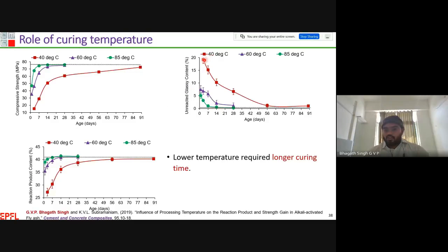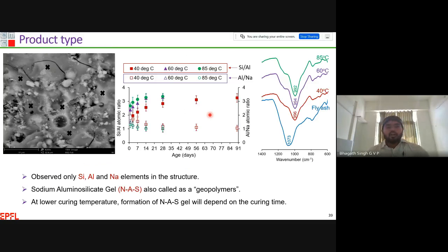We have three curing temperatures. At 40 degrees Celsius, you can see the dissolution is taking place very slowly. In the case of 60 to 85 degrees Celsius, you can see the dissolution is complete by 7 to 14 days. Again, we tried to identify which type of product is formed at these curing temperatures. If you increase the temperature from 40 to 60 to 85, then the silica to aluminum atomic ratio shows a more or less similar trend to the compressive strength.